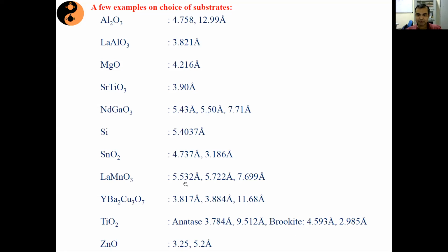Suppose if I have to grow an anatase phase of TiO2 with lattice parameter 3.784, which substrate I should choose? The answer is, if you look at this 3.784, it matches very close to lanthanum aluminate. So I will pick up this particular substrate. Okay. So these are some of the tricks that people generally follow.